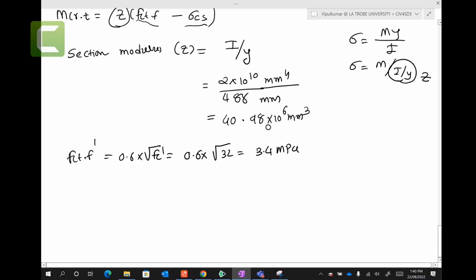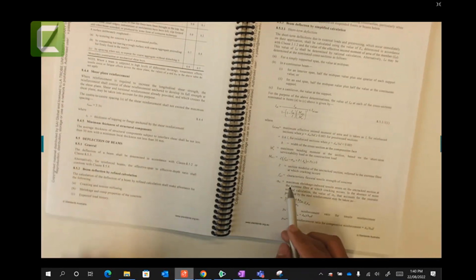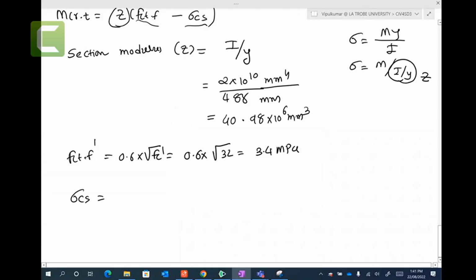For this sigma cs, what is sigma cs? It is given here. It is the maximum shrinkage-induced tensile stress on the uncracked section at the extreme fiber at which cracking occurs, and in the absence of more refined calculation, the value that accounts for the restraint provided by steel reinforcement may be taken as follows. Here pw is the web reinforcement ratio for tensile reinforcement, and this one is the ratio for compression reinforcement. Let me copy the equation for you: sigma cs is equal to (2.5 pw minus 0.5 pcw) over (1 plus 50 pw), times Young's modulus times shrinkage strain.